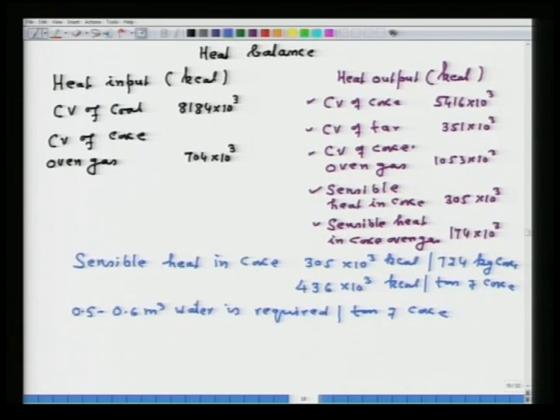Now, the water is sprayed on the hot surface of coke, which is at 1200 degrees Celsius, and the water is vaporized along with the contaminants, because water nearby the integrated steel plant is not pure, it has a lot of contamination. So, all those contaminations are evaporated into the atmosphere. So, a large amount of emissions are discharged into the environment. That means along with this, airborne coke dust is also discharged